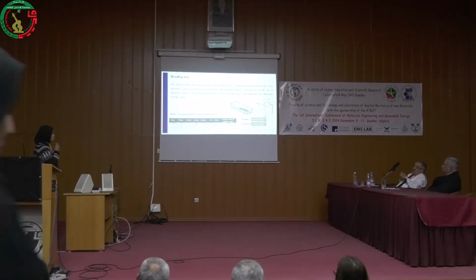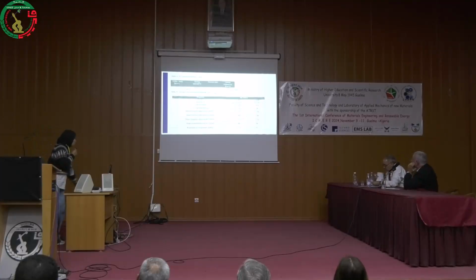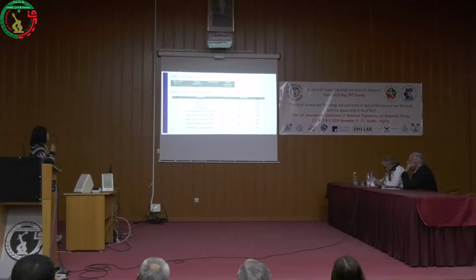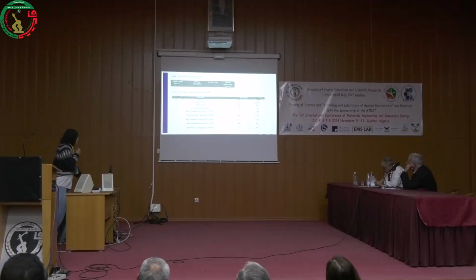1.3. So for the bending test, the material we're using in this study is a sandwich material with an aluminum Nomex honeycomb core. It is supplied by Euro Composites and intended for the aerospace industry. The structure of this type of sandwich consists of two-dimensional Nomex cells placed in the plane of the sandwich with aluminum skins. Table 1 shows the specimen dimensions for the three-point bending test, while Table 2 and Table 3 show the mechanical properties of both the skin and the Nomex core. Which leads me to my next point, which is the experimental procedures.